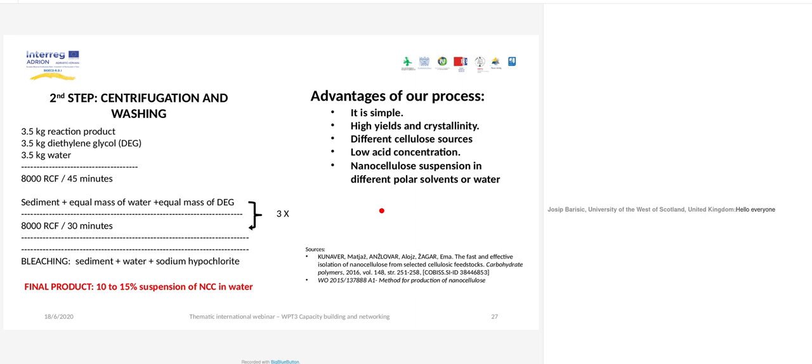The yields are quite high, because the yields in the lab are about 60%. In the pilot plant production, it's around 45%, which is really quite high. And of course, the price for this production is very low. I would say that it is at least 5 to 10 times less than the standard procedure with this high concentration of sulfuric acid. So the process is not a secret. You can use it in your lab, but if you start an industrial production, see you in the courtroom.